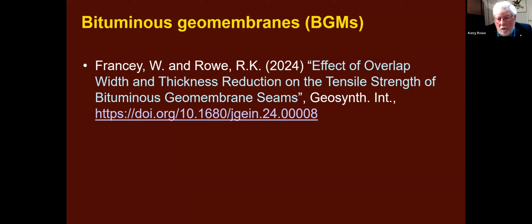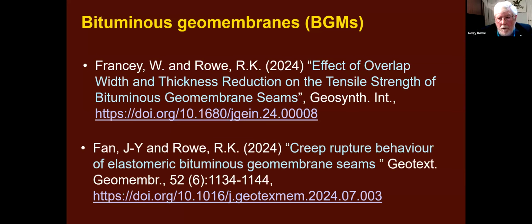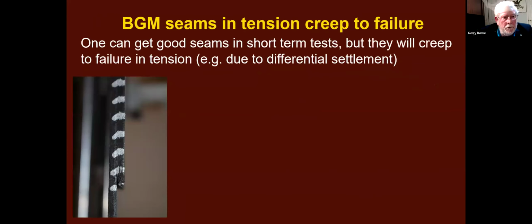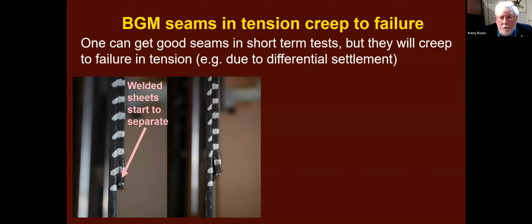Now, we have two papers. Eric referred to one of them with Francey, and we have another one that's come out recently with FAN. This is one of the first things we did, very simple. We took a BGM that was welded, we painted some white horizontal lines across the weld, and we subjected it to a sustained tension. And with that, we began our monitoring, and we saw after a short time, those white lines were no longer horizontal, and it was starting to open up at the bottom.